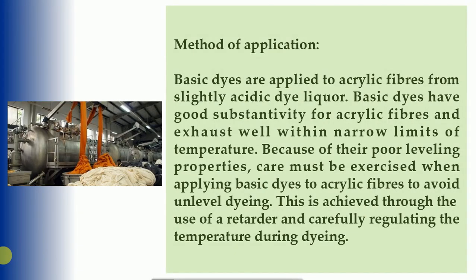Method of application. Basic dyes are applied to acrylic fibers from slightly acidic dye liquor. Basic dyes have good substantivity for acrylic fibers and exhaust well within narrow limits of temperature. Because of their poor leveling properties, care must be exercised when applying basic dyes to acrylic fibers to avoid unlevel dyeing. This is achieved through the use of a retarder and carefully regulating the temperature during dyeing.